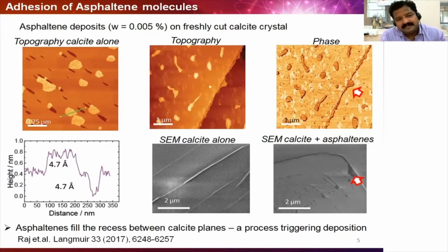So from these examples of asphaltene deposits on different substrates, depending upon the nature of the substrate, it forms different conformations, and depending on these conformations to the substrate, it influences different properties, physical properties like adhesion, stiffness, or preferential orientation to deposit across the surfaces.